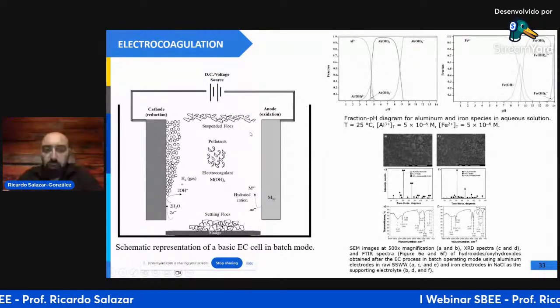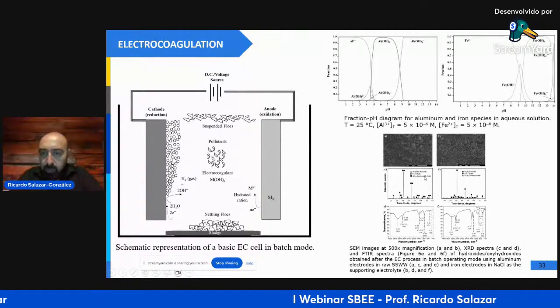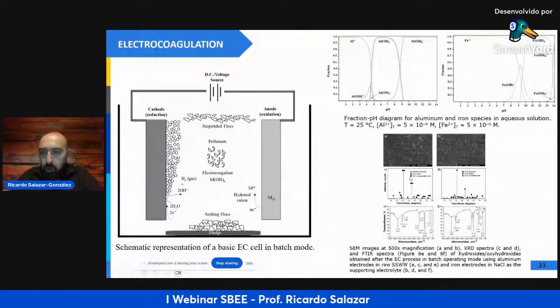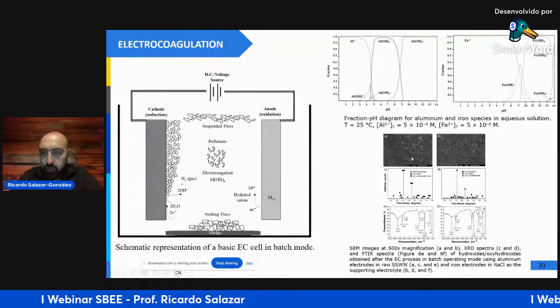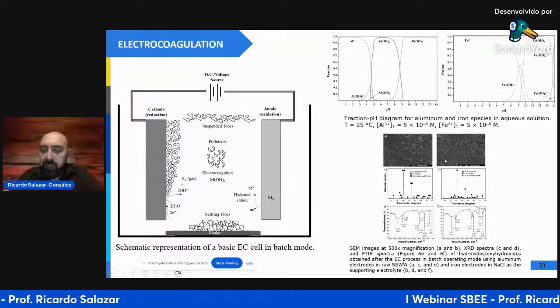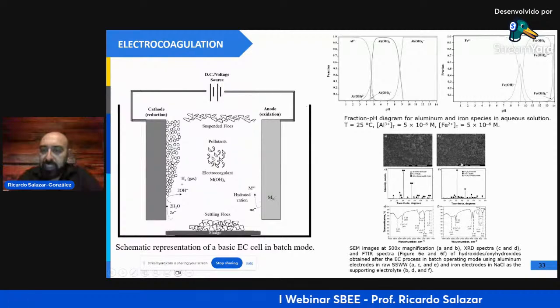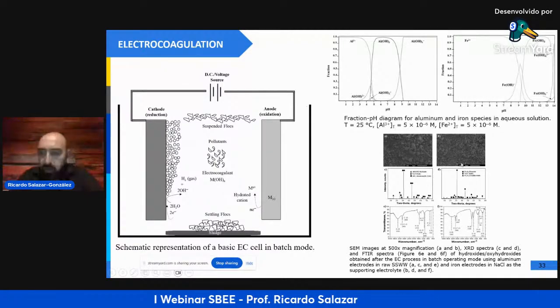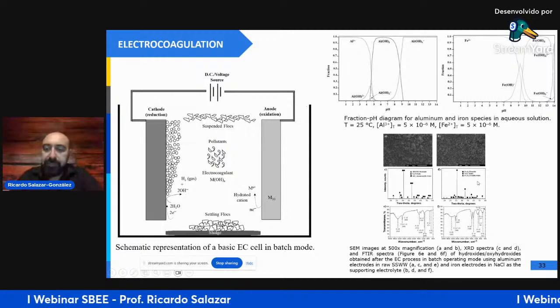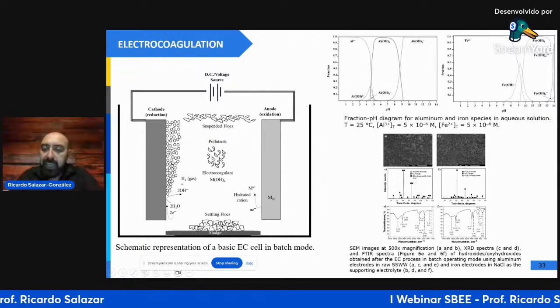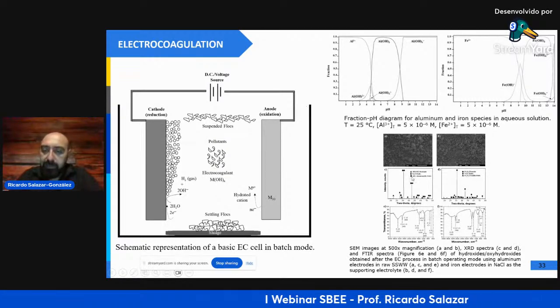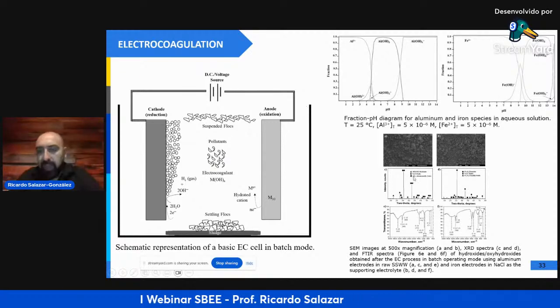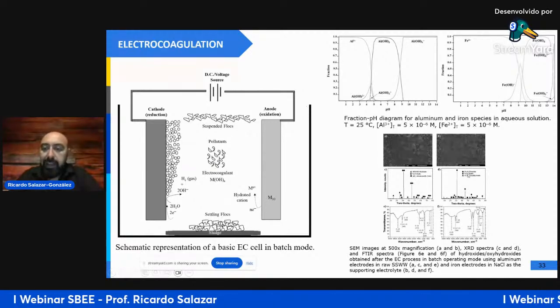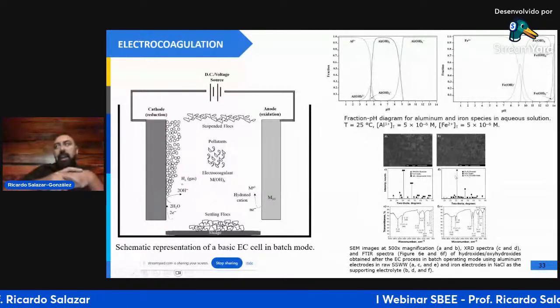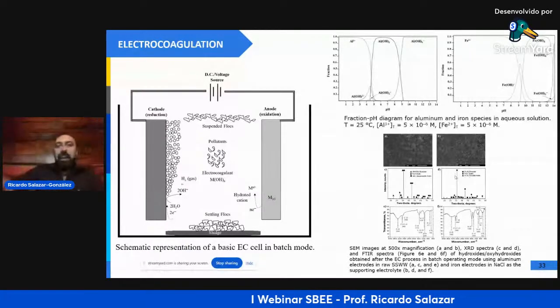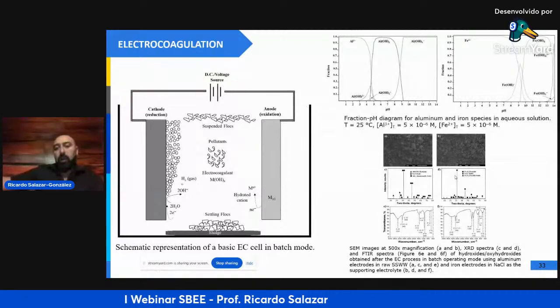And during the anodic oxidation, we can produce different species of aluminum or iron, depending on the electrode that you use in the experiment. For example, in the case of iron, we can produce hematite or different iron oxides. This kind of oxide from iron or from aluminum can remove a very high variety of pollutants from wastewater.